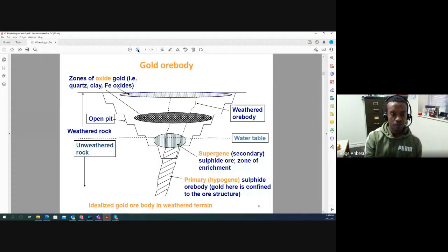The vast majority of it, 90 plus, 95% plus, is going to be waste rock. But the gold is most likely going to be confined in that sulfide mineralization. So for this kind of ore body or zone, you're going to require some kind of concentration method before you go with leaching. Mineral processing then comes into play, and it's all about what we do to separate the sulfide, which contains our target gold.